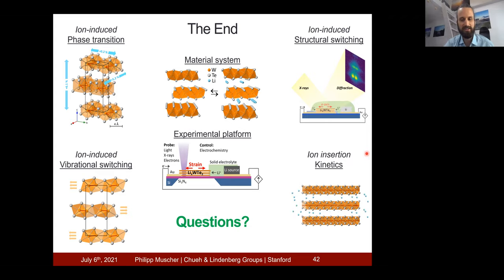Yeah, thanks for the great question, Shaked. So the diffusion coefficient is essentially the main unknown in the system. I know, for example, the time profile from the experiment, and I know the spatial profile from the flake that we're using. And the unknown is really the diffusion coefficient. So the way I operated it is I run the simulation at different diffusion coefficients, and then I see which diffusion coefficient lines up with the experimental result. So that's how I got that. So it's an iterative regime, essentially. Does that answer your question?